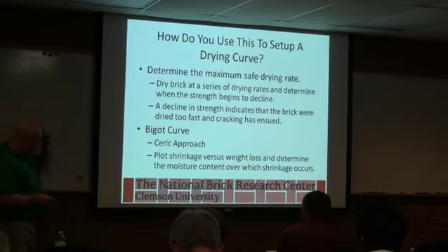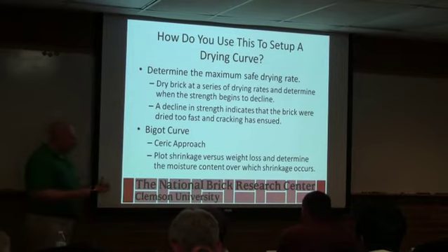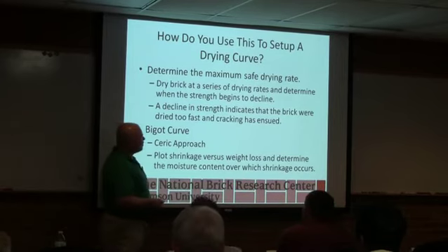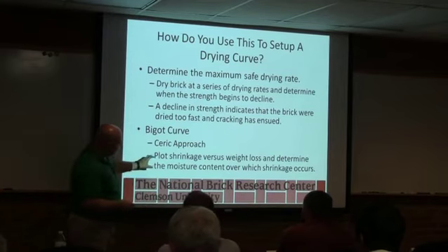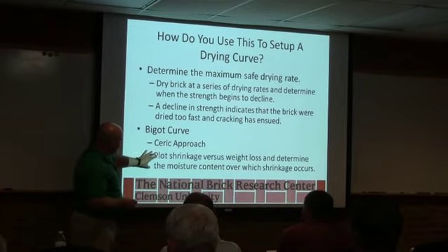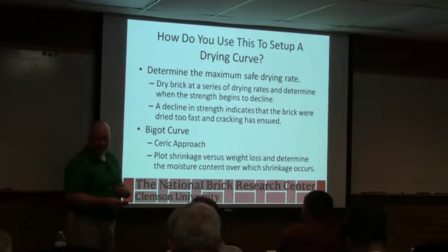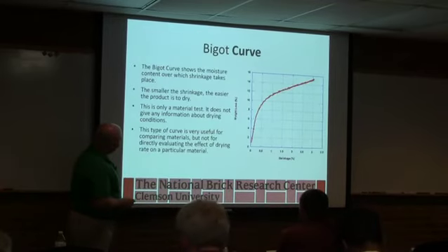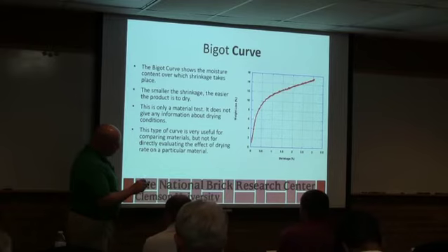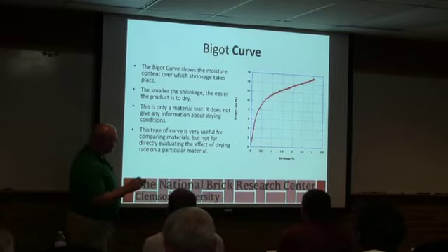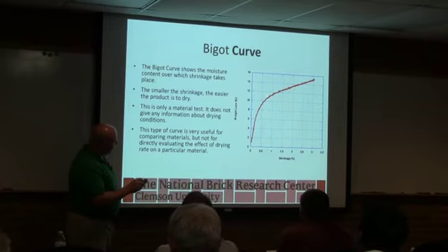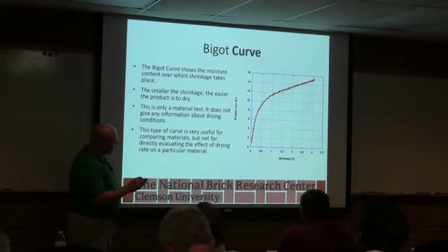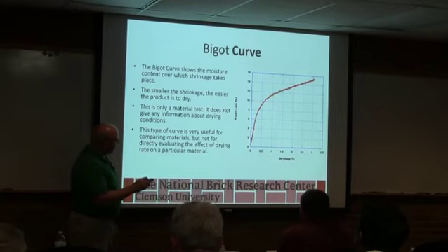They plot the shrinkage versus the weight loss, and based on their experience, that tells them something about how the material is going to dry. So if you ever deal with Silica, you send Christoph some material, he sends it to us for a drying test. So we do those kind of curves. So the Bigot Curve looks something like this, where we've got weight loss and shrinkage. So what he's looking for is what percent of moisture, what's a critical moisture content, where shrinkage is basically getting close to stopping, and then he can speed up.